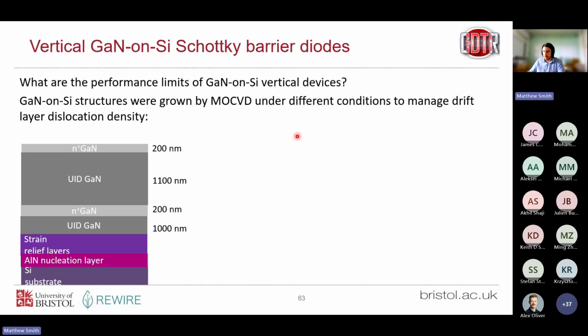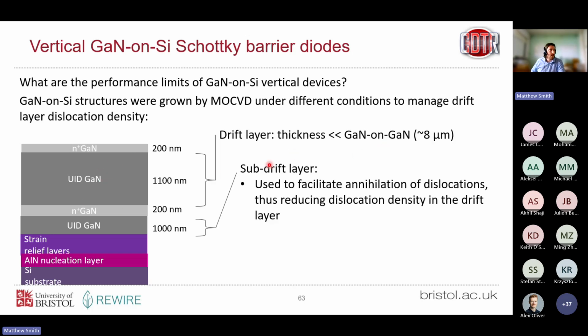This is material supplied by the University of Cambridge, Professor Rachel Oliver's group. So we have about a micron thick of our UID drift layer. That's a typo, it should be 1 micron. And we have this subdrift layer here where the aim is to annihilate as many dislocations as we can in this region and then make this region as high quality as possible. So reducing the dislocations in this region by playing tricks in the growth and trying to annihilate dislocations down here.